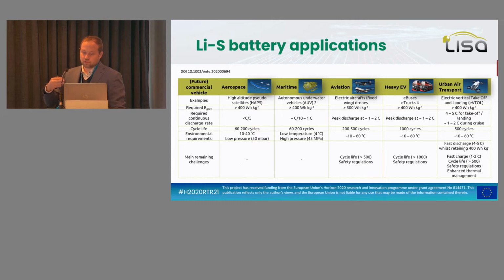Together with the issue that we have regarding the power, to give you an idea, all the curves that you see are cycled at C/5 or C/10, for the solid state, for example. And when you reach 2C, you are more or less at 70% of the C/5 beginning of life, no? So cyclability and power are really two drawbacks that are not solved today. But the more you increase these parameters, the more applications you will get. It will be very tricky to address a passenger car for power, etc., and volume. But we think that for this application, this is something completely possible.